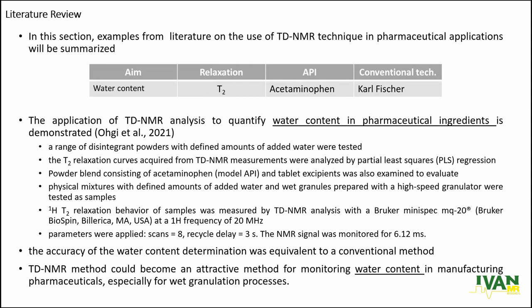In this section, I will summarize some examples from the literature on the use of the TD-NMR technique in pharmaceutical applications. In this study, TD-NMR analysis is used to quantify water content in pharmaceutical ingredients. A range of ingredient powders with identified amounts of added water were tested. They obtained the T2 relaxation curves, and a powder blend consisting of a model API and tablet excipients was also examined. They conclude that the accuracy of the water content determination was equivalent to the conventional method, which is Karl Fischer. And they show the TD-NMR method could become an attractive method for monitoring water content in manufacturing pharmaceuticals, especially for wet granulation processes.